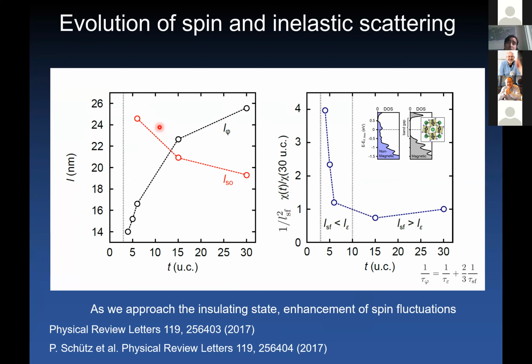magnetoconductance. The new phenomenon that is observed here, that is different also from LAO STO interfaces, if you're familiar with the field, is that the dephasing length of the system estimated by these fits has a very strong evolution as a function of thickness. So this is not the case, for example, in LAO STO. As we go below the 10 unit cell limit, we observe a very sharp variation of the dephasing length. And as you know, the dephasing length is something that gives us information on the magnetic susceptibility of the system. So this indicates that there is really a strong enhancement of the magnetic susceptibility of the system as we approach this insulating state. So a strong enhancement of spin fluctuations is observed by magnetotransport.